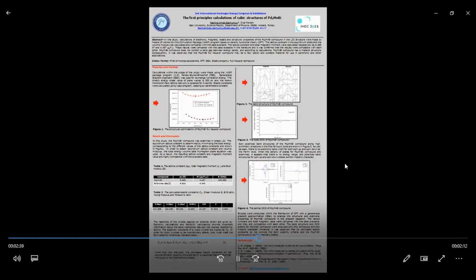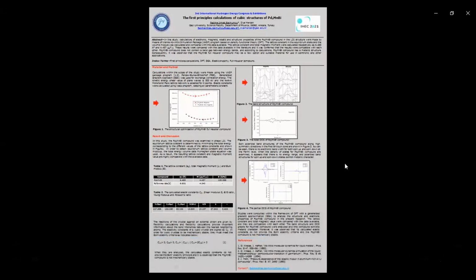The response of the crystal against an external strain is given by the elasticity calculation. For the cubic structure, the elastic stability criteria are given by the below equations. When they are analyzed, the calculated elastic constants do not provide the stability criteria, and it is observed that the Pd2MnBi compound is not mechanically stable.